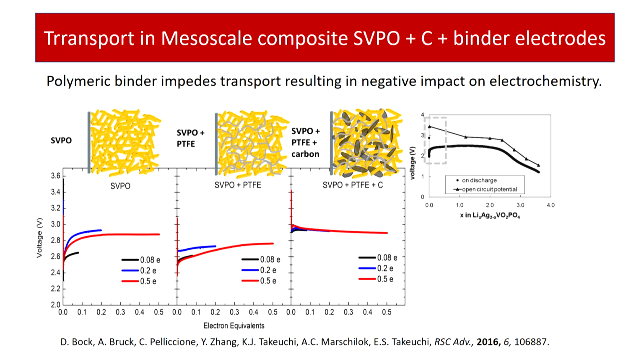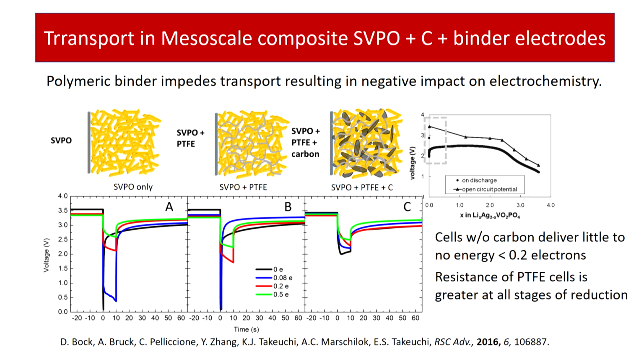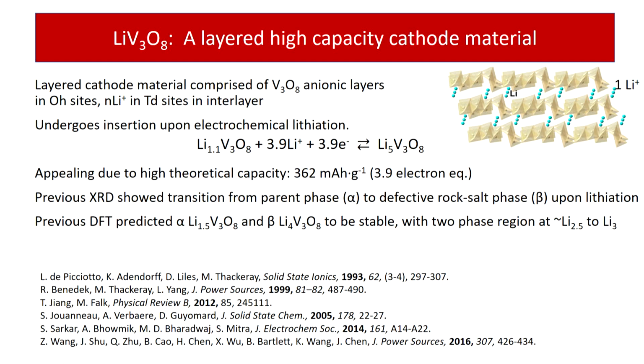The other thing that EDXRD allowed us to probe was the impact of binders. You know, binders have been viewed as not really mattering. They're there, but they don't matter too much. And it turns out that if binders are insulative, they negatively contribute to the function of the battery. If we have a material that can generate its own conductive network and we have a binder present, the behavior is even worse. Of course, adding carbon overcomes this, but this has led to, for us, a field of inquiry looking at conductive binders to minimize the impact on transport of electrons throughout the electrode.